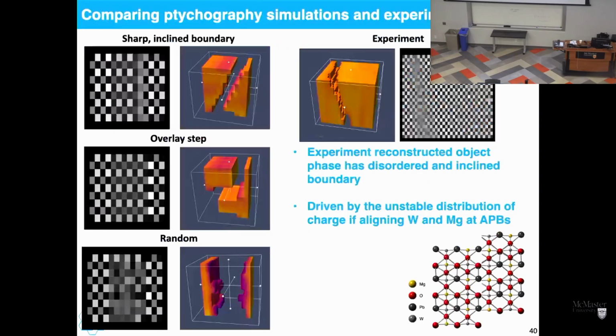But what we can do instead is to map out, it should have been overlapped on that, but what you can see is there's this boundary here. The chemical order of the magnesium and tungsten are the blue magnesium and red tungsten sites, but at the boundary you get this white contrast moving across that image. Why is it moving across the image? Because the boundary is inclined relative to the electron beam. And we can also see this chemical intermixing.